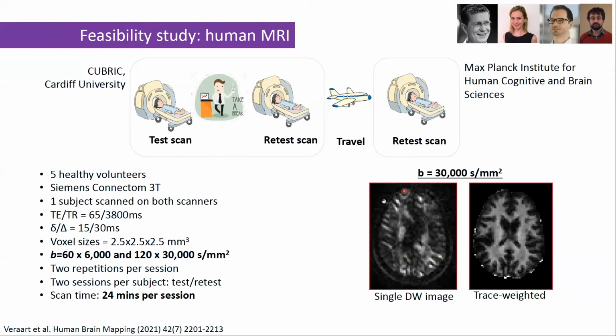And just to show a little bit of image quality, a single diffusion weighted image at b=30,000 is shown on the left-hand side. The powder average signal at b=30,000 is shown on the right-hand side. And I hope you appreciate that this signal and its contrast to noise ratio is quite appealing and impressive. And it really shows that there's little signal decay inside of the axon. You can really go to very high b values without losing signal and without hitting the noise floor.